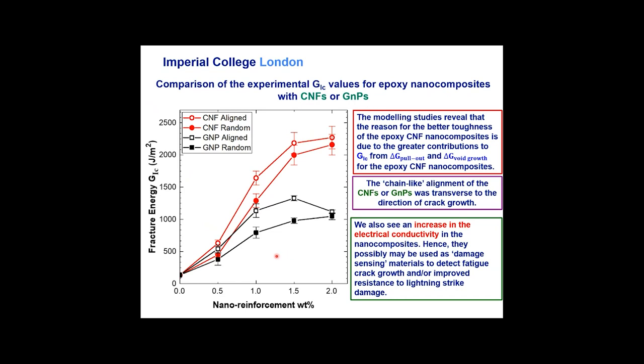The other interesting thing we see is that for several of the levels of added nano reinforcement, until we get too much, when it makes the adhesive too thick, too high viscosity, then the alignment of the material by applying the AC field gives you slightly higher toughness for both the CNFs and the graphene nanoplatelets than for the random material.